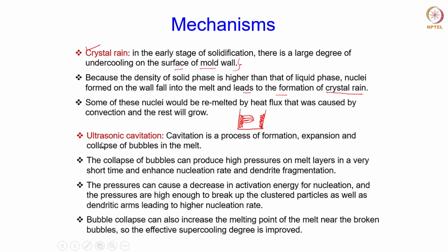Then we also talked about the ultrasonic cavitation process, which is applied for grain refinement during solidification. Cavitation is a process of formation, expansion and collapse of bubbles in the melt, which leads to either a high nucleation rate or breakage of the dendrite arms, both leading to a higher nucleation rate or grain multiplication, and ultimately giving rise to a fine grain size in the solidified metal.